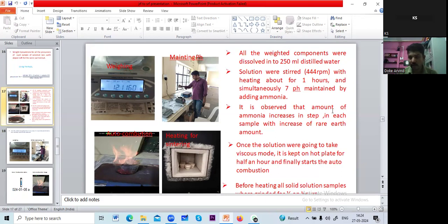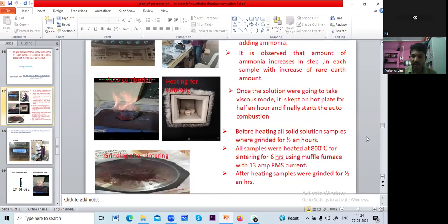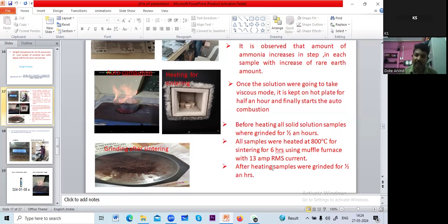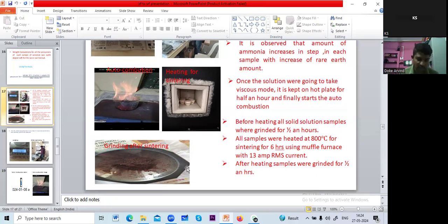It is observed that the amount of ammonia increases in step in each sample with increase of rare earth amount. Once the solution becomes viscous, it is kept on a hot plate for half an hour and finally the auto-combustion method starts. Before heating, all the samples were ground for half an hour. All samples were heated for sintering for 6 hours using a muffle furnace with 13 amp RMS current. After heating, the samples were ground for half an hour. Finally, the nanoparticles were obtained.